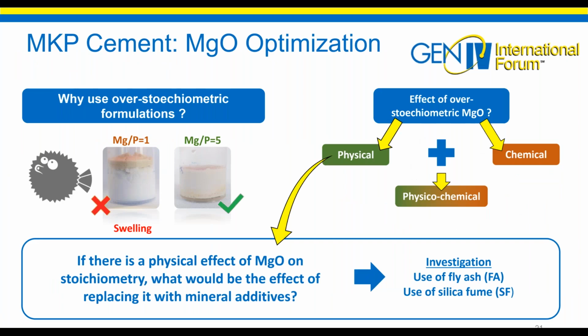The answer is very simple. The stoichiometric matrix with a molar ratio of magnesium to phosphate equal to 1 is characterized by swelling, which is not the case of an over-stoichiometric matrix. What is the effect of this excess of magnesium oxide? Is it a chemical effect, a physical effect, or a physico-chemical effect?